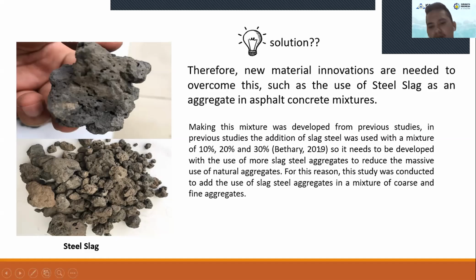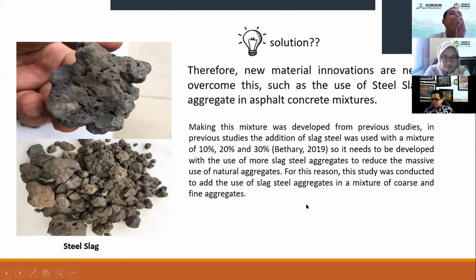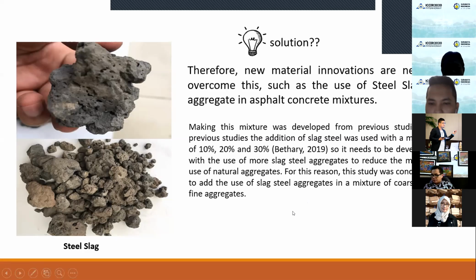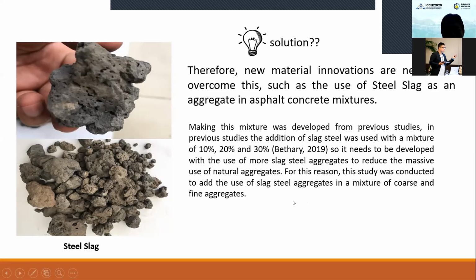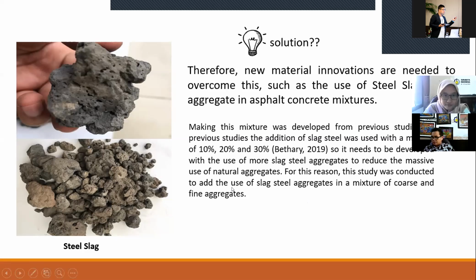Solution: therefore, new material innovations are needed to overcome this, such as the use of steel slag as an aggregate in asphalt mixture. Making this mixture was developed from previous studies. In previous studies, the addition of steel slag was used with mixtures of 10%, 20%, and 30% (Bethary, 2019). So it needs to be developed with the use of more steel slag aggregate to reduce the massive use of natural aggregate. For that reason, the study was conducted to add the use of steel slag aggregate in a mixture of coarse and fine aggregate.